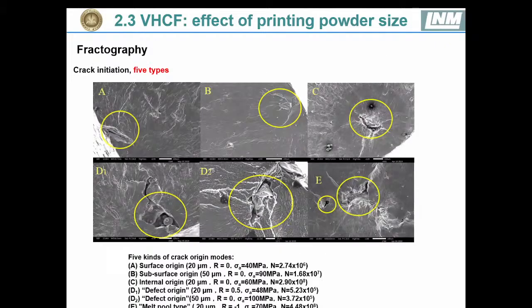And in addition, we also observed crack initiation using scanning electron microscopy. Here, 5 types of crack initiation modes are classified. One is crack initiated from the surface. Here you can see that it may be due to surface roughness or some other surface defect. Also, cracks may start from the subsurface and internal cracks, and the lack of fusions and pores are shown in these figures. Also a crack initiated from an internal defect finally grows and forms a fish-eye pattern, which is shown in figure C.